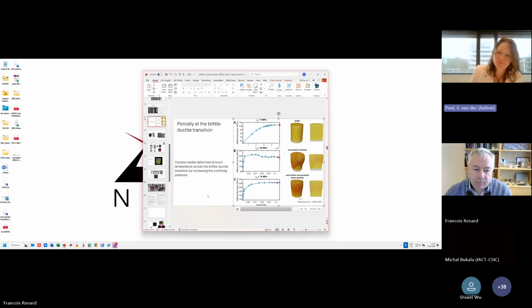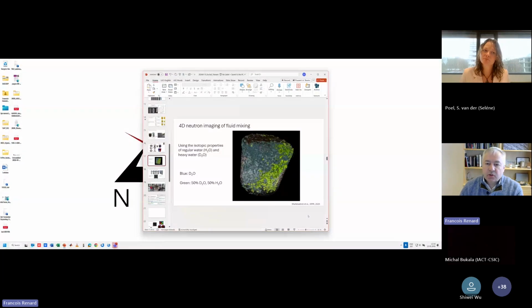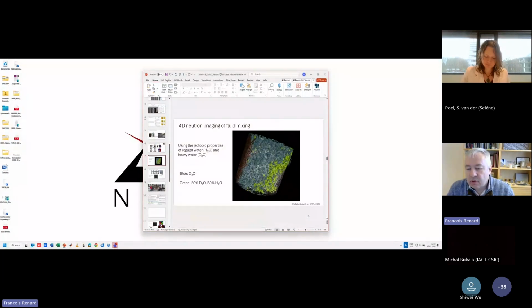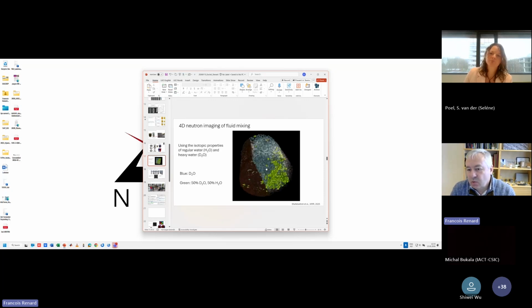Is playing with deuterium less impacting the kinetics than adding bystander ions such as iodine to the solutions for calcite precipitation? So first, deuterium is water, and the kinetics of dissolution and precipitation in heavy water is not very different from water. The only advantage is the density difference between heavy water and water. Here we use either heavy water or a mixture of the two, and the density difference is less than 5%. Whereas when you use iodine, usually you need quite a high concentration. So if you want to do fluid mixing with iodine, you have two fluids with quite different densities. Normal water and water with 3 molar of iodine, the density difference starts to matter.